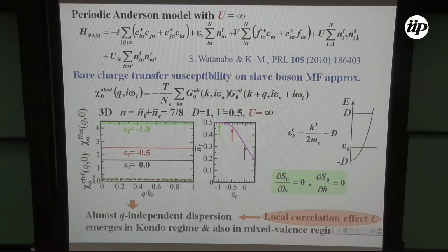We also did a much more solid calculation on the basis of the same Hamiltonian and calculated the so-called particle-hole susceptibility, corresponding to the f-c charge transfer. Then it is shown that it is almost constant up to kF. So in this sense, the valence transition is almost Q independent, which is very consistent with that. Valence transition is essentially a local phenomenon, because of the f electron and conduction electron energy considerations.